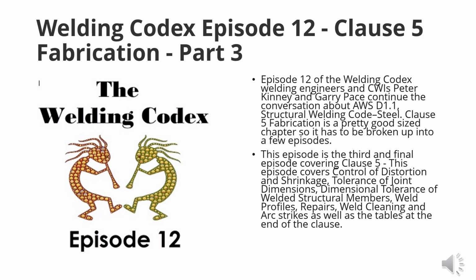If you're going to use 5/16, it may be used provided suitable backing is used and the final weld meets the requirements for weld size. So that gets back to using that backing of iron powder or flux or some similar material to weld that up. So you can't just go in there on a 5/16. You got to have some suitable backing. Correct. And I've never used iron powder for anything. I have heard some stories of it, but subarc flux is the one I've normally seen used. I think one is it's relatively cheap and easy and readily available.